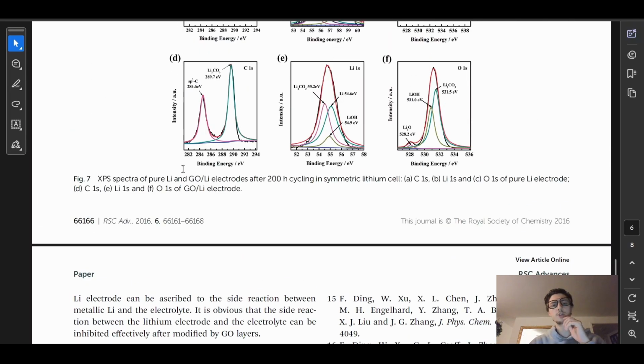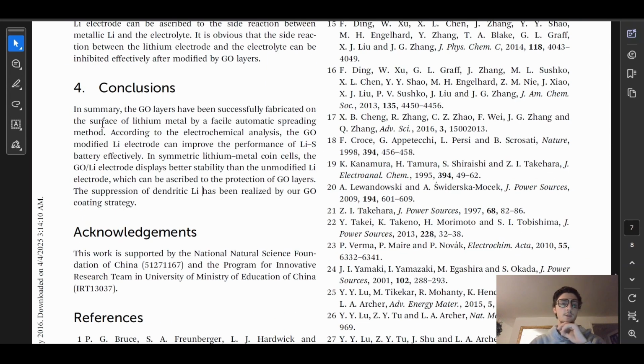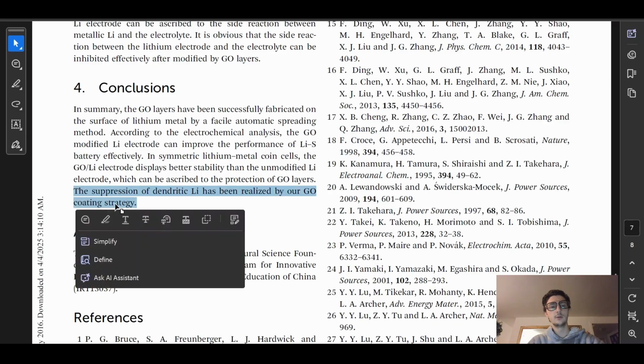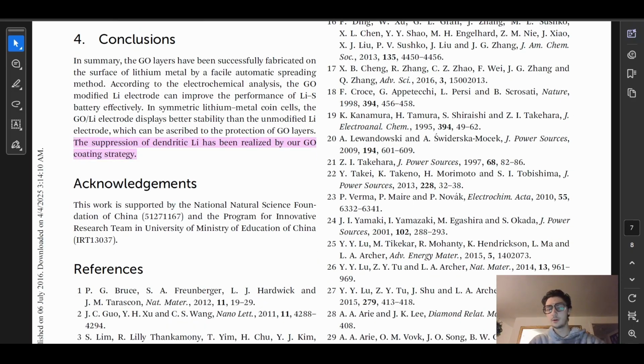So I know the last couple sections here with these graphs were confusing, but let's just finish off and see what the conclusions are. In summary, the graphene oxide layers have been successfully fabricated on the surface of the lithium metal by facile automatic spreading method. According to the electrochemical analysis, the graphene oxide modified lithium electrode can improve the performance of lithium sulfur battery effectively. In symmetric lithium metal coin cells, the graphene oxide lithium electrode displays better stability than the unmodified lithium electrode, which can be ascribed to the protection of graphene oxide layers. The suppression of dendritic lithium has been realized by our graphene coating strategy. Very cool. I'm going to highlight this to end off the reading of the article.